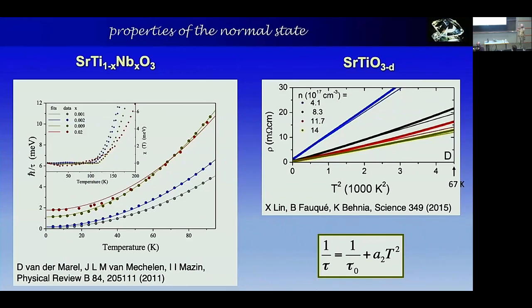But in all cases, if you plot it this way, you find straight lines. And so these straight lines also tell you that you have this form for 1 over tau. It's a constant residual value, plus something proportional to T squared. And that's true up to around 100 Kelvin. Beyond that, you actually go into a different crystallographic phase, and there's no longer this behavior also.